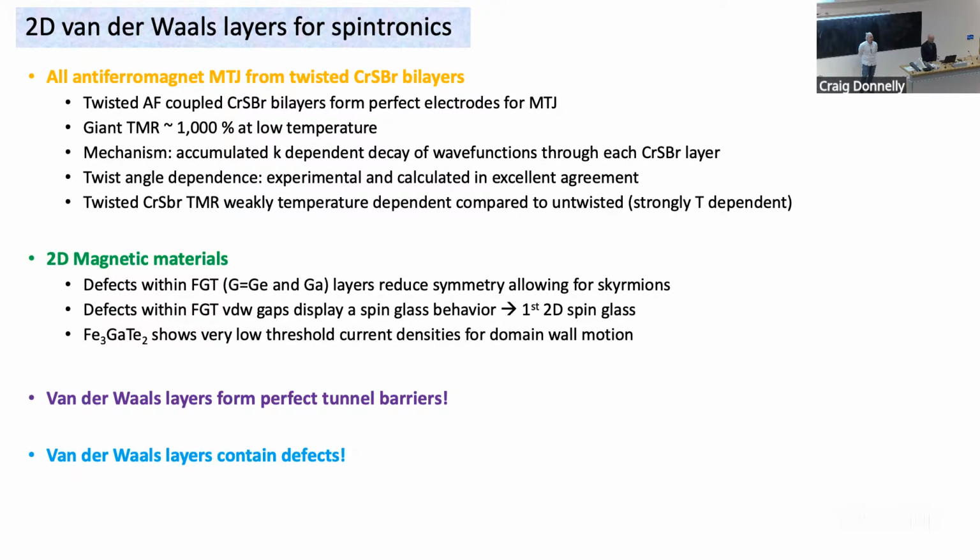As I said, I think it's very different, because in our multilayers you have a few angstroms of cobalt and nickel cobalt, and slight variations are inevitable. That will locally change the anisotropy, for example, and lead to pinning sites. Here, the layers are certainly more perfect. It doesn't mean they're totally perfect, because we see these iron vacancies. If these iron vacancies are not uniform, that could give rise to some pinning of the domain wall. But do you see stochastic jumps over large distances? Do you see effects like that?